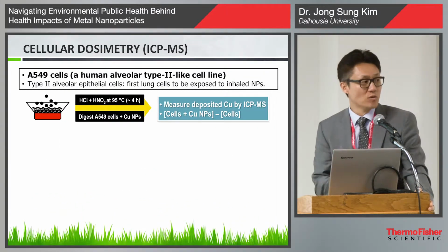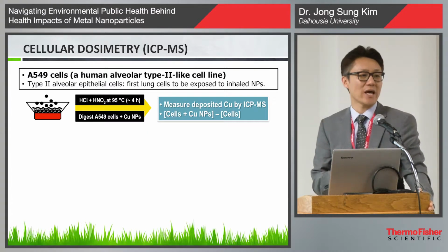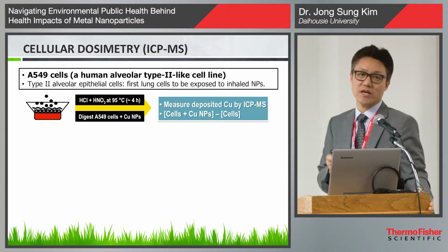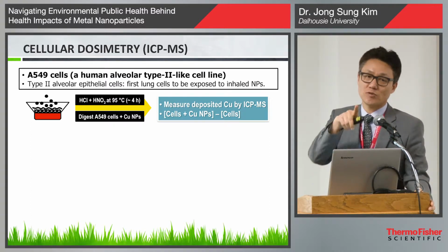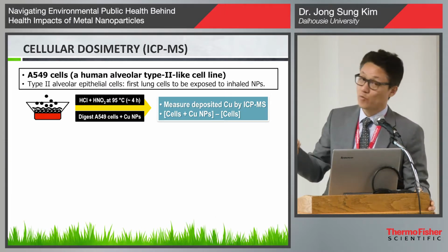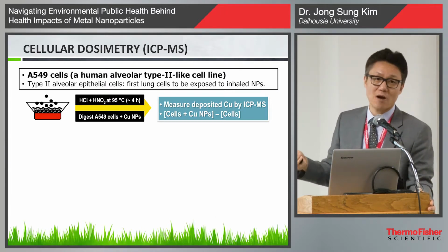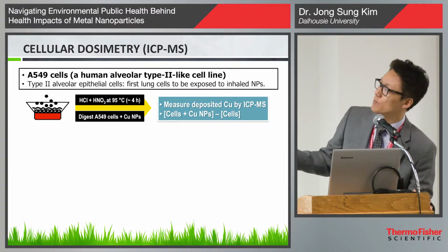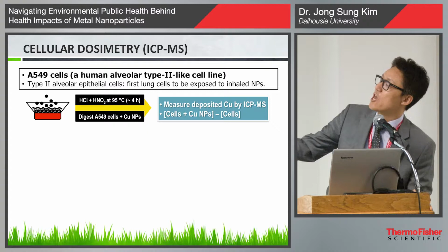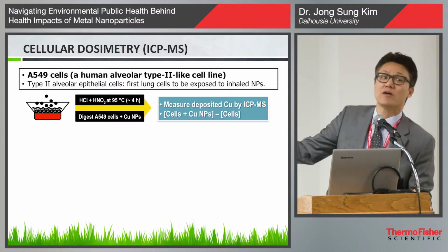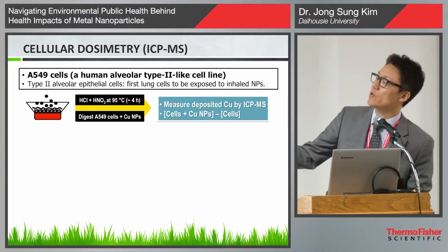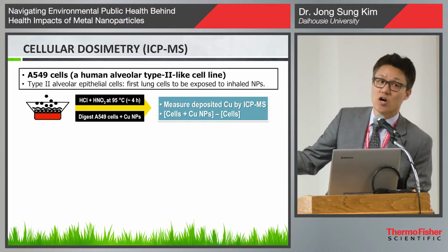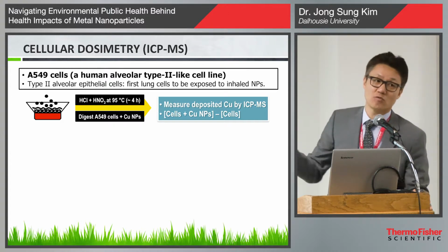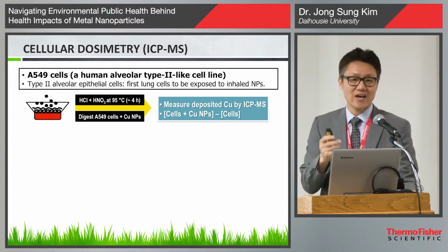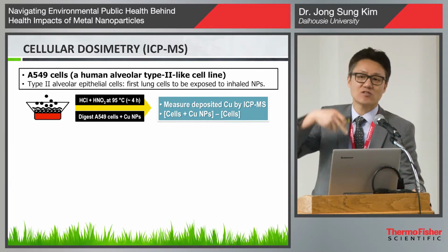So to support our hypothesis, we'd like to measure copper and iron concentration in cells and media. Since we deliver nanoparticles to lung cells with air, we can do dosimetry, which means measuring copper or iron concentration using ICP-MS. We deliver nanoparticles to lung cells, then digest the cells and nanoparticles and measure metal concentration, as well as metal ion concentration in media. The reason is that if the media has more metal ions, they can translocate to different organs through the bloodstream.